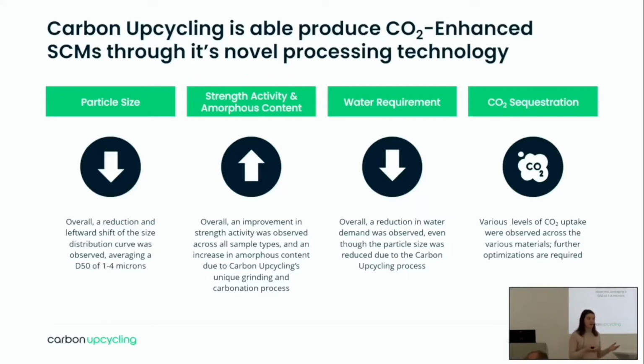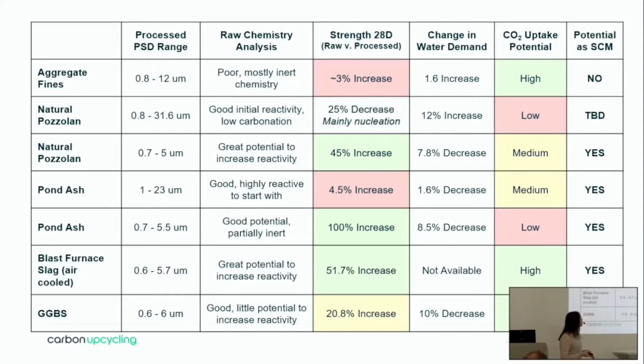CO2 mineralization is based upon chemistry. So some materials are really good for carbonation, some don't present a good opportunity for carbonation. And so we have to weigh the balance of, we get a lot of a strength improvement, but how much carbon can we capture? And when we looked at the results from this study, we saw there was a range in both strength improvement and CO2 uptake. So this table is a lot, so I'll try and summarize it for you because this was the findings of our program with the GCCA.